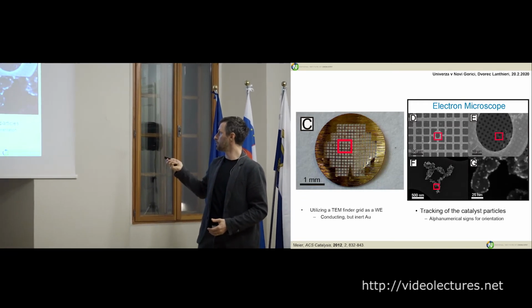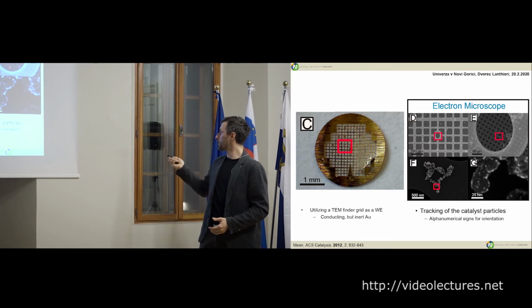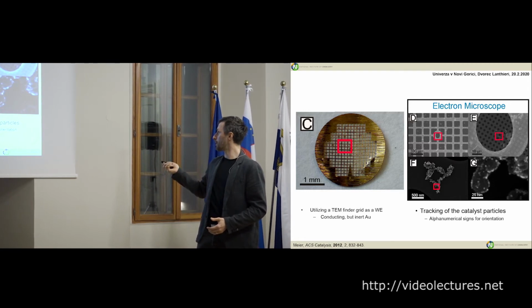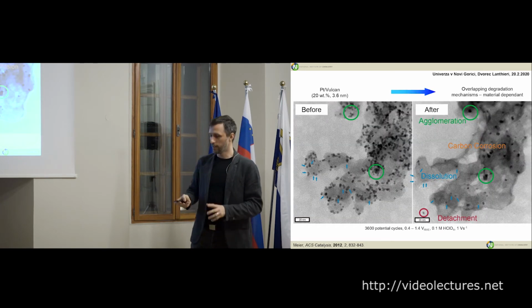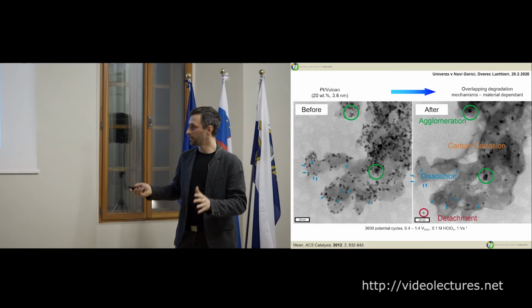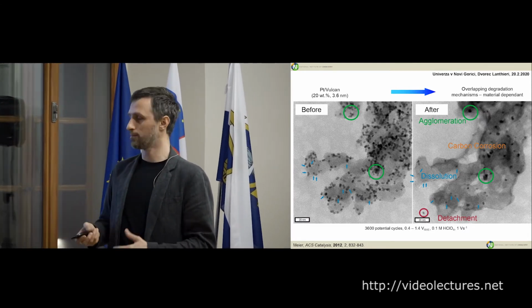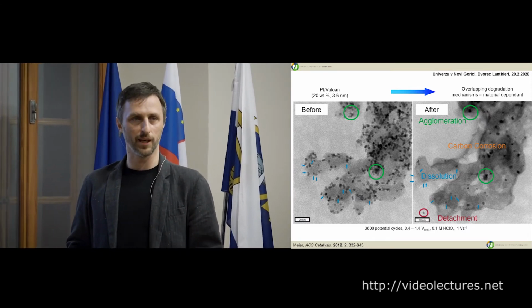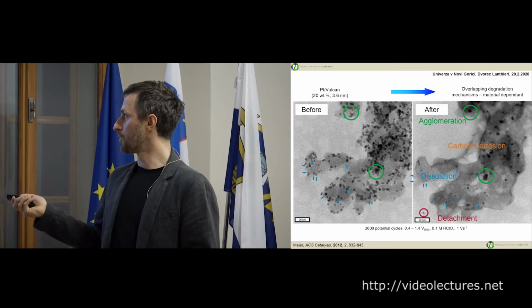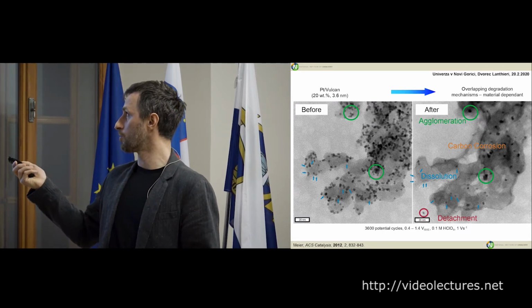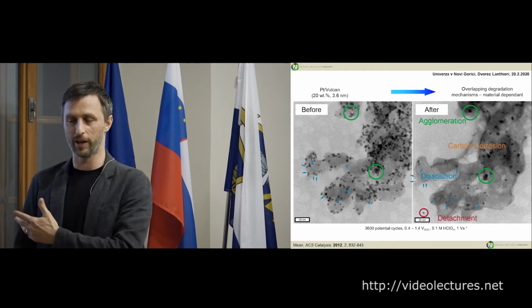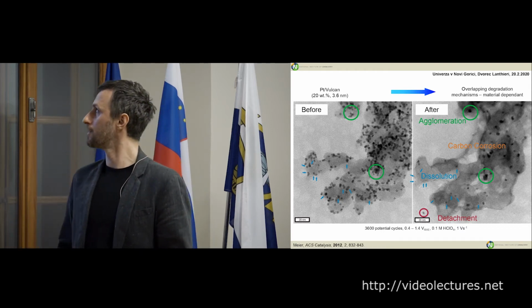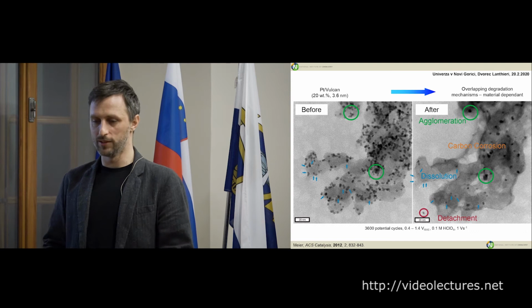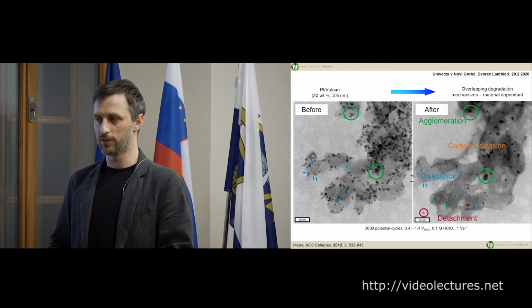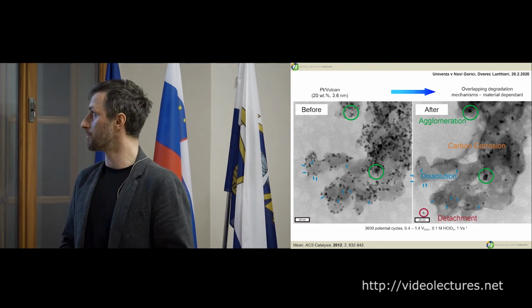There's O, we zoom into O, and then you find this catalyst, this part. So this is nanoparticle, this is SEM. Now if we look at one typical event, we can see that there's much more mechanisms happening at the same time. It's not just one. So you have the detachment, dissolution, carbon corrosion, and agglomeration on practically one picture. So it's a mess. So it's really impossible to do it unless we really observe the same location.